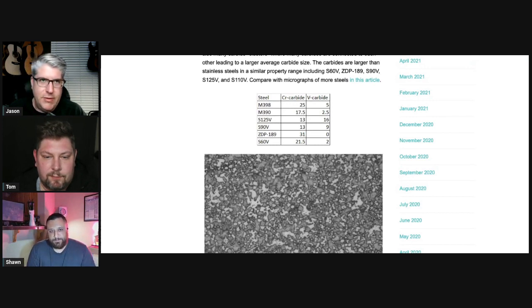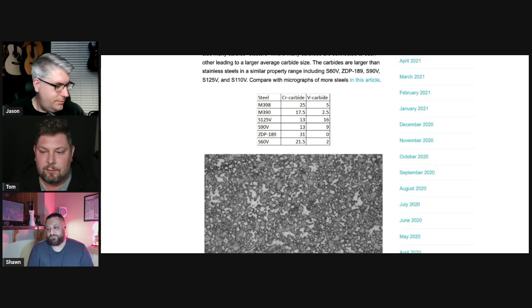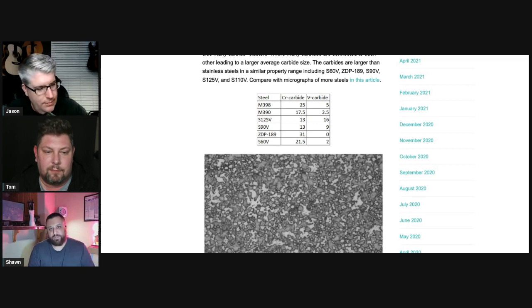When you guys hear the term 10V, they call it 10V because approximately 10% by weight of the steel matrix is vanadium. So the vanadium is a carbide, in the purpose of a knife. In the knife world, it's a carbide forming element. Yeah, I mean there is some vanadium that's in solution, but the thing about it that's confusing is you don't get 10% vanadium carbide just because there's 10% vanadium. It doesn't work like that. There's actually 17% vanadium carbide in 10V.